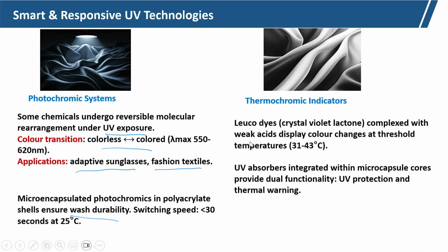Leuco dyes like crystal violet lactone, complexed with a weak acid, display color changes at a threshold temperature between 31 to 43 degrees Celsius. So, UV absorbers integrated within the micro encapsulation core provide a dual functionality, UV protection and thermal